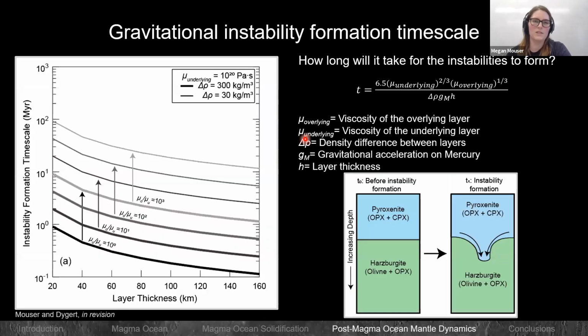So the first step is looking at the instability formation timescale. So how long it would take to go from basically this layered scenario to the formation of the instability. So we're starting that downwelling process. And so you can see the equation that we used up here. Again, we're considering all of these different parameters in here. But this figure over here is just a compilation of what this equation is telling us, where we have these different layer thicknesses and at which time scale they would form.